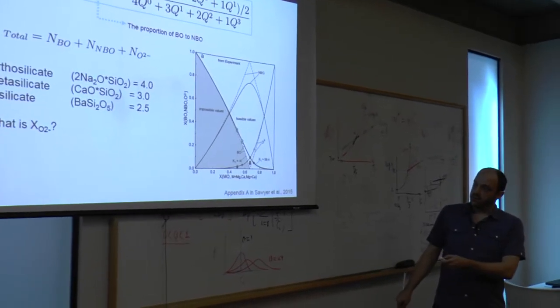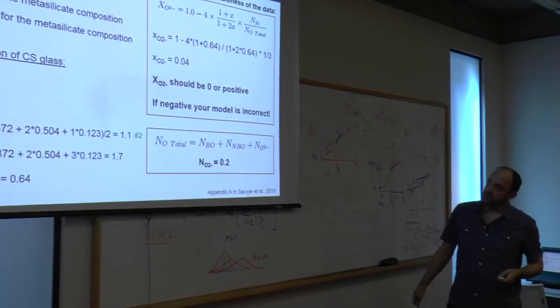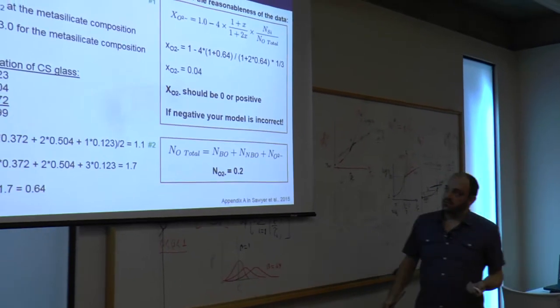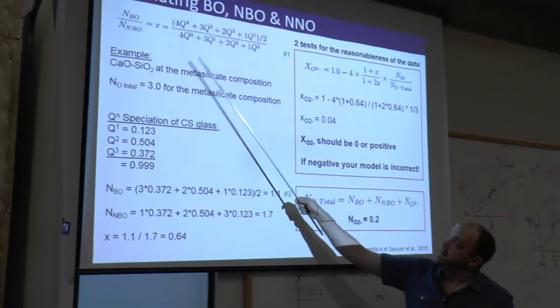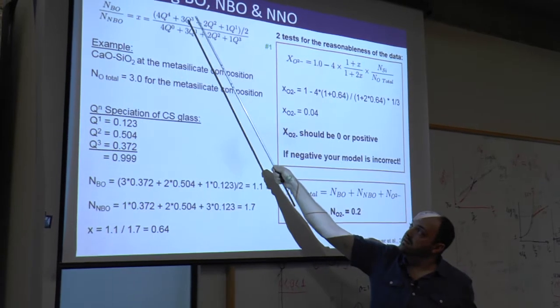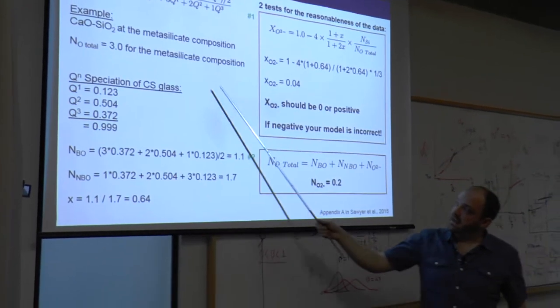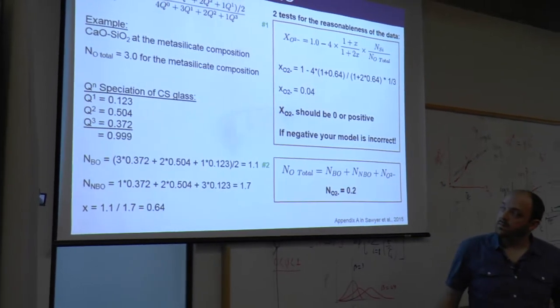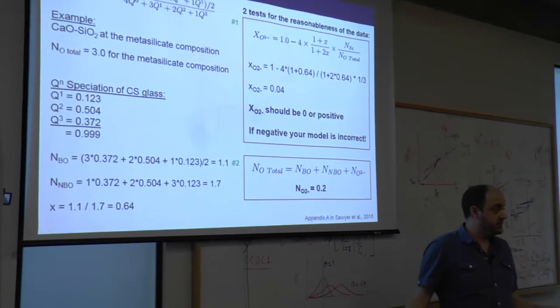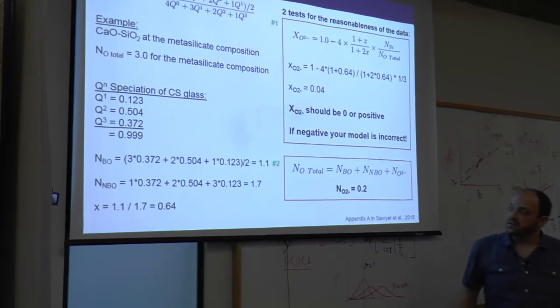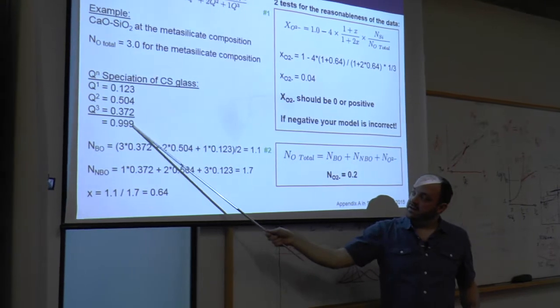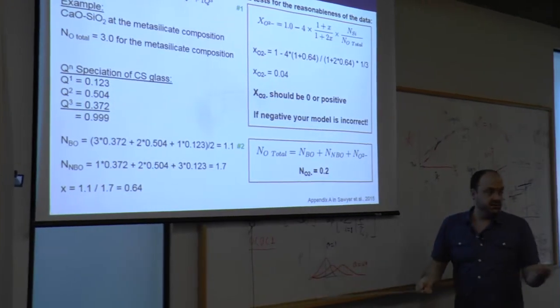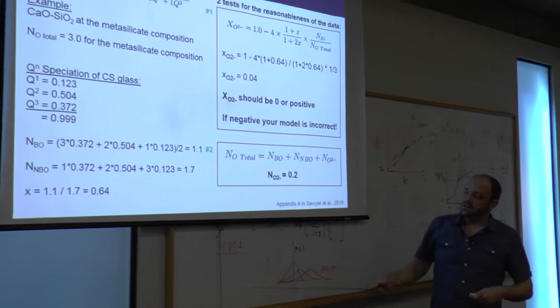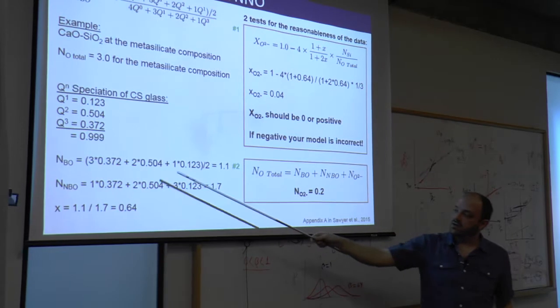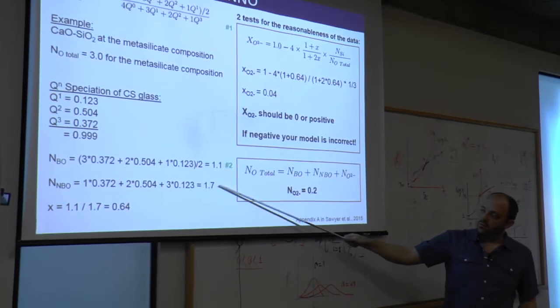So if we can't measure this O2, this non-network oxygen, how do we go about doing that? I've done a little example here of calcium metasilicate, so CaSiO3. Here's our proportionation between the moles of bridging and non-bridging oxygen. And this speciation for this glass is an interpretation of a Raman spectra determining the Q1, 2, and 3 in this glass. You notice that there's a little bit of error here. It doesn't add up to 100%. It adds up to 0.99, so take that into consideration. But you can chug through the simple math, and you can see that the molar proportions of bridging and non-bridging oxygen are 1.1 and 1.7.